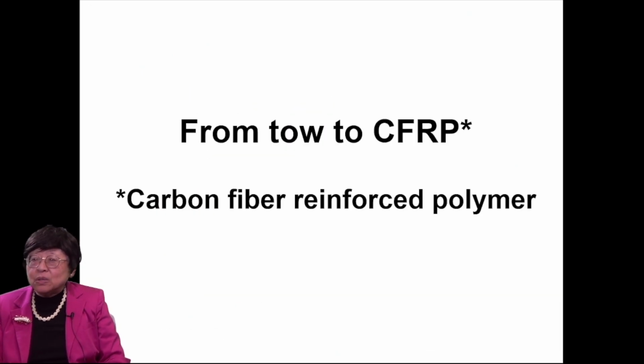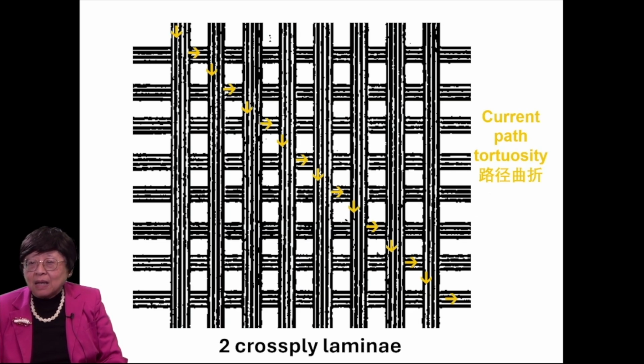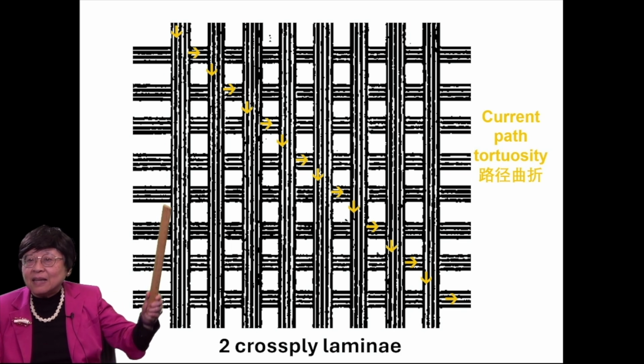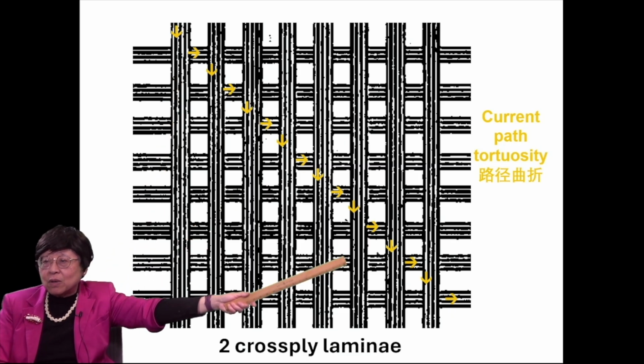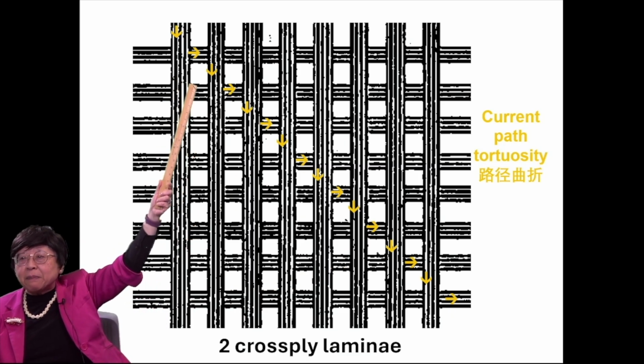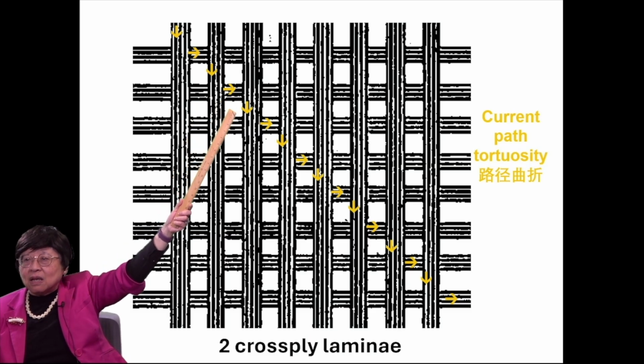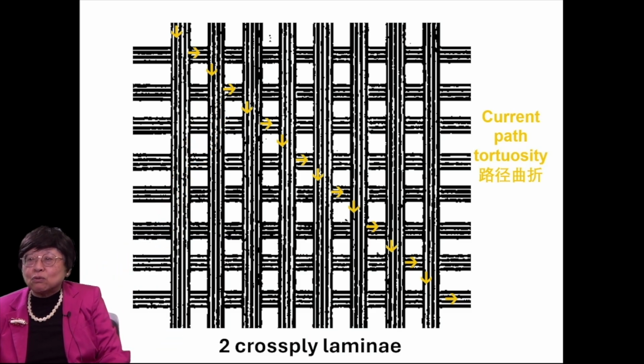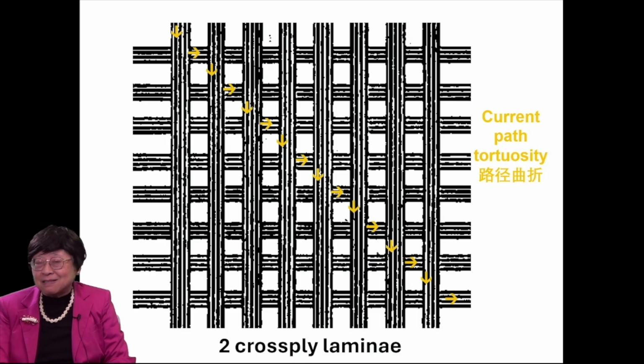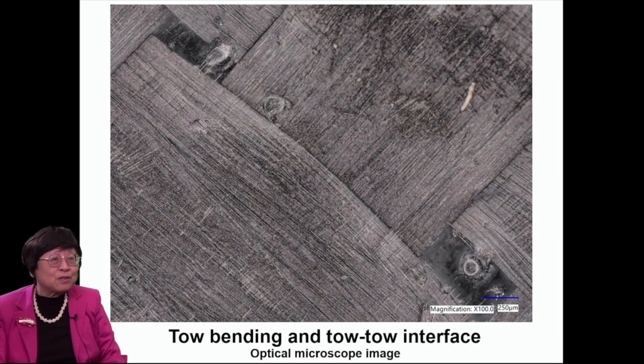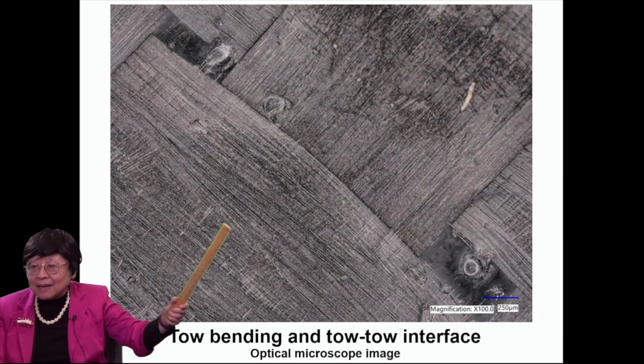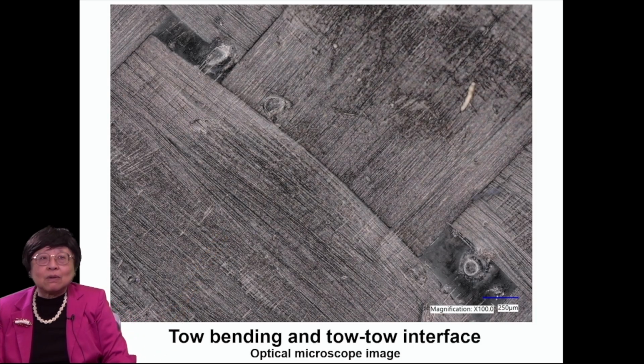Now I move from tow to CFRP, which is carbon fiber reinforced polymer. This is a two cross-ply laminate, and you can see that if you go in this 45 degrees direction, the current path has to change direction. This is current path tortuosity. That's not coiling, but it's a bit like coiling. Okay, and that should increase the inductance. The tow bending and tow-tow interface should also increase the inductance.